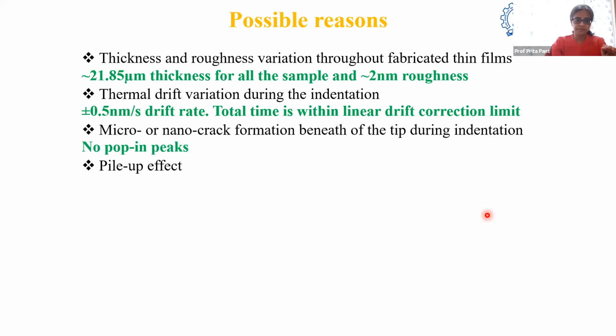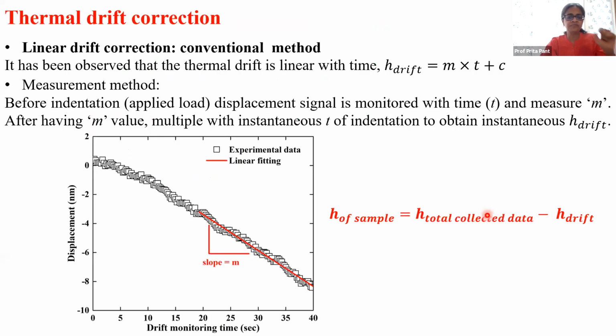There were no pop-ins in our experiments, which are indicative of displacement bursts when a crack happens. And there were no pileups. We imaged our samples very carefully. There were no pileups. So we said, okay, the easy reasons are ruled out. But let me just take you on a slight detour for this thermal drift, because again, if there are students here, you should think about it.